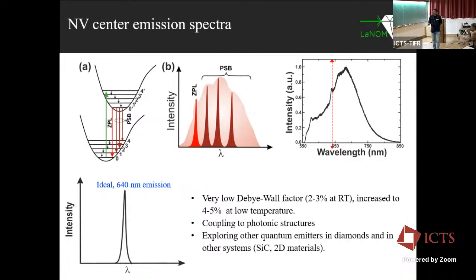One parameter we use in the NV literature is called the Debye-Waller factor, which is the amount of emission going into the zero phonon line compared to the total emission. And the NV center has only a 2 to 3% Debye-Waller factor at room temperature. If you cool the system down to low temperature, you can suppress these phononic contributions, but the emission is still only 4 to 5%. And the emission rate is also very, very slow in the system.